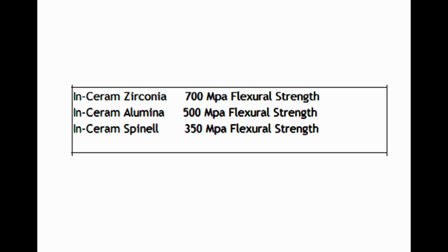If we look at all three glass infiltrated ceramics in the In-Ceram family, there is a very interesting pattern. When it comes to strength, In-Ceram zirconia tops the list and it has the highest flexural strength. At the other end, In-Ceram spinel shows the lowest strength, while In-Ceram alumina sits somewhere in between.